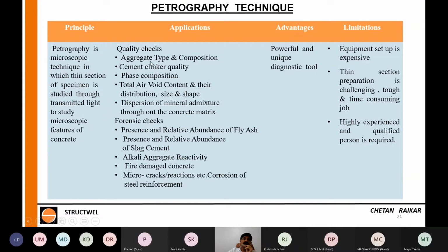So you can use petrography for quality checks of aggregate type and composition, cement clinker, phase composition, phases in cement manufacturing, total air void content, and dispersion of mineral admixture throughout the concrete matrix. You know, when you have added mineral admixture or pozzolanic material at the mixer at site, and you want to know whether the dispersion is proper throughout the body of concrete.